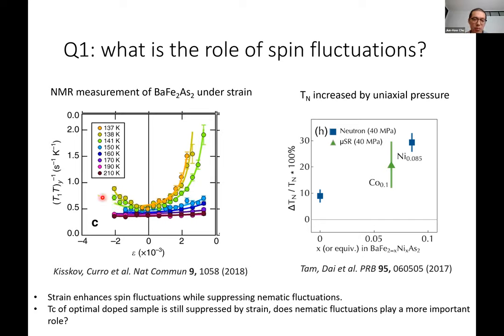So that basically implies that, at least for the optimal doping where there's no long-range magnetic and structural order, when you're applying strain, you're not only suppressing the nematic fluctuation, but you're also increasing the spin fluctuation. But still, the superconductivity is suppressed by strain. So does that imply that the nematic susceptibility is playing a more important role, or the spin fluctuation has already changed fundamentally as you're applying strain and is therefore no longer helpful for superconductivity?